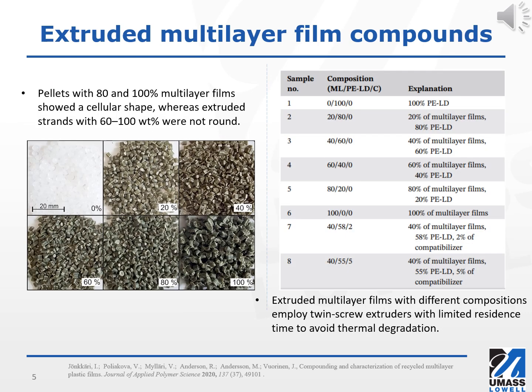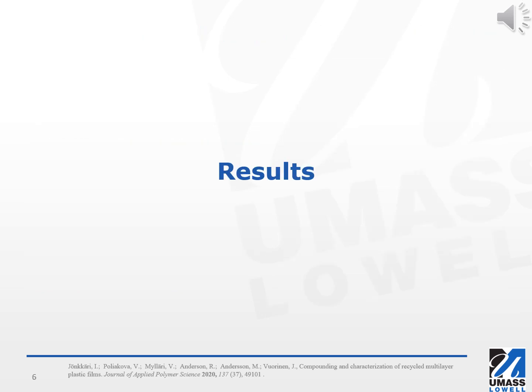Here you can see the pellets that were manufactured with a range of different concentrations of multilayer films. In order to prevent thermal degradation, multilayer films that are extruded with a variety of compositions were used in twin screw extruders with a short residence time. The pellets that included between 80 to 100 weight% of multilayer films had a cellular structure, and the cross sections of the extruded strands that contain between 60 to 100 weight% of the multilayer films were not spherical at all.